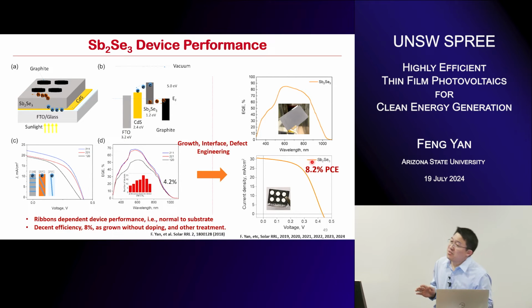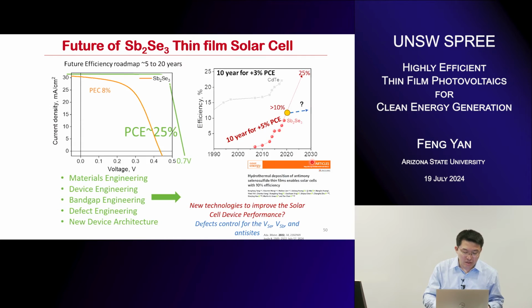Even we call it a growth interface, it's barely like the 8% of cadmium telluride 50 years ago. It's just to grow the film and make a simple device. And gradually, I think this is a very promising solar technique. Pretty stable in air, not like the perovskite. Pretty wide band gap that can be further tuned. So this is a very nice technique, and we continue to work on this.